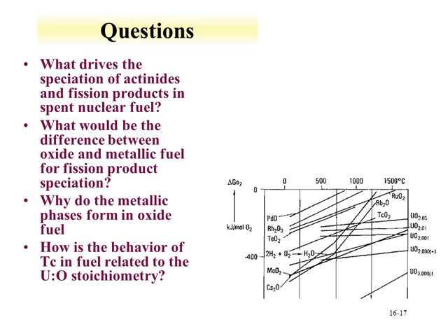And how is this behavior related to the technetium speciation in oxide fuel? Well, again, depending upon where your UO2+x lies and the temperature. So for instance, if it's UO2.05, when the temperature is below, let's say, about 800, technetium will be the oxide as opposed to the metal phase.